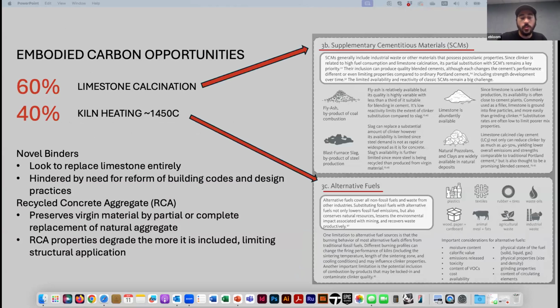And so one of the most common practices today to substantially reduce emissions associated with cement is through the inclusion of supplementary cementitious materials. These are materials that look to partially replace the amount of lime and clinker content. These are often limited by availability or the extent to which they can replace lime before affecting structural properties. And for some, such as fly ash or blast furnace slag, these are byproducts of already carbon-intensive processes. And so with their substitution in cement mixes, their benefits may be overstated from a carbon perspective.